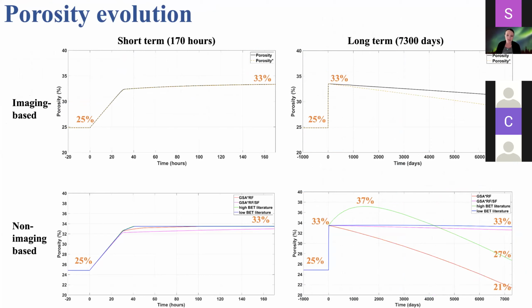Now, in terms of understanding how this impacts porosity, we can see the simulation results from using the image surface areas on the top and the results from the other simulations on the bottom. At the shorter time scales, we have an increase to about 33% with really little variation in the different simulations. But at longer time scales, we can see the evolution of porosity can be quite different. In some cases, you end up with quite large increases in porosity before larger decreases. And thinking about these longer time scales, some of those variations are quite extreme.